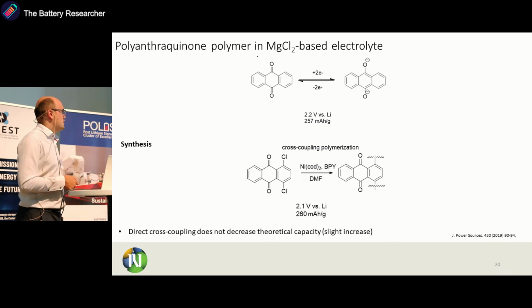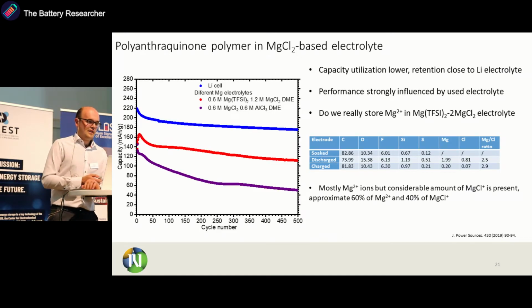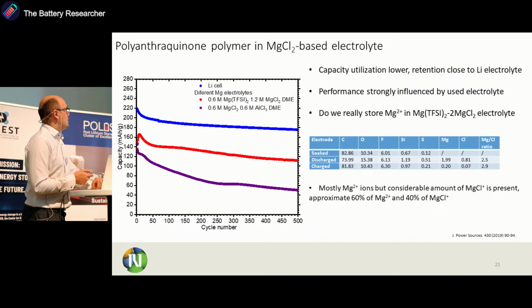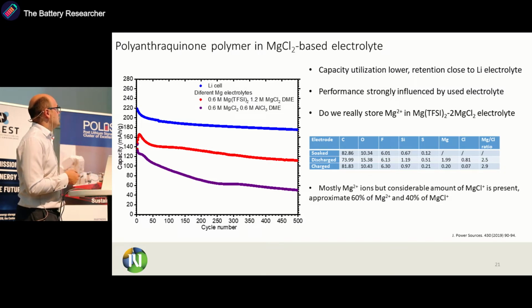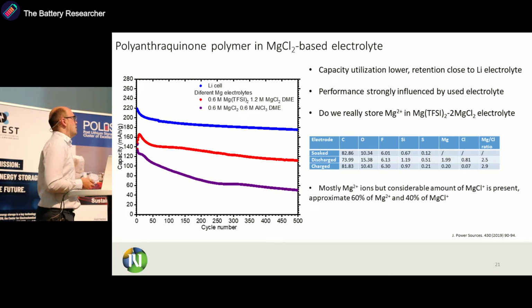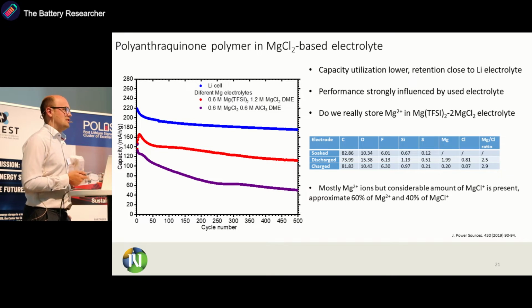If we utilize this cross-coupling polymerization with nickel cyclooctadiene, we can get this polymer. We do not lose any capacity because we connect the groups together, and we slightly increase it because we remove these two hydrogens, and the redox potential stays roughly the same. And then we apply it to the electrochemical testing, and like I said before, we benchmark it first with lithium, and then we tested 2 magnesium chloride containing electrolytes. So magnesium TFSI with magnesium chloride, and magnesium chloride with aluminum chloride. These were 2 of, let's say, the most popular electrolytes in the past years.